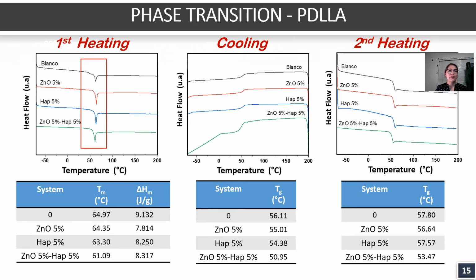denotes the presence of a certain alignment of the polymeric chain produced by the uniaxial stretching that the polymer fluid experiences in the spinning process. In the ternary system, this transition occurs at slightly lower temperature compared to the rest of the systems. On the other hand, during the cooling and second heating cycle, only a second order transition, typical of an amorphous polymer, was presented, which shows a marked decrease due to the incorporation of a mixture of nanoparticles.